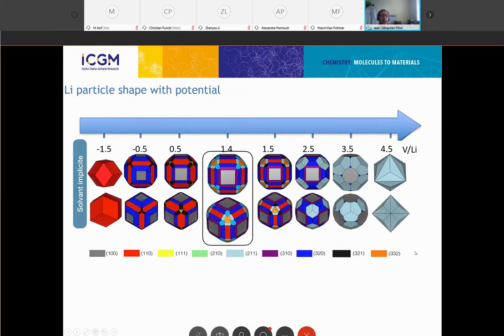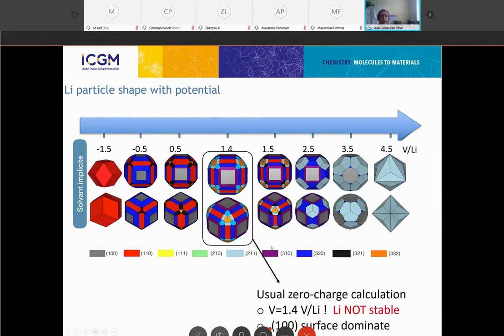If I redo that for lithium, looking at the uncharged system, I find that the uncharged system for lithium is associated with a potential of plus 1.4 volts relative to lithium. So when you are modeling an uncharged lithium surface, you are modeling an unstable system, because at 1.4 volts the stable form of lithium is not metallic lithium, it would be lithium plus. So you are computing a system that is not experimentally possible.